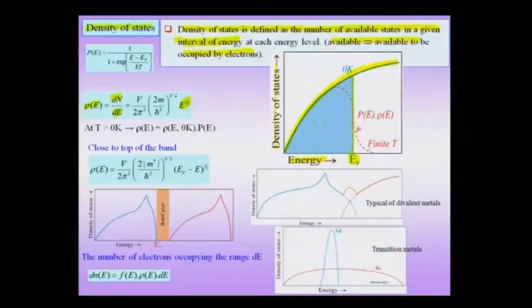But we had also pointed out that when I want to track the number of energy levels at any finite Kelvin temperature, then I need to multiply my function by what is known as the Fermi Dirac function, and I would do the same thing here to find the density of states at any finite Kelvin temperature. That means at T greater than 0 Kelvin, to find the density of states, I will multiply the density of states at 0 Kelvin, which is of course the blue shaded region in the curve, by the P of E, which is given by the Fermi Dirac function, and therefore, this function close to the EF will start to develop this kind of a curved region. In other words, there will be a small tail.